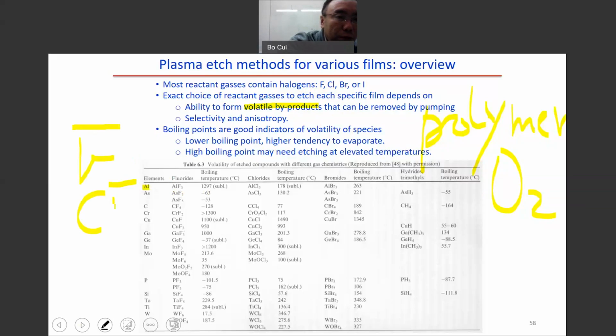For example, for the case of aluminum, if we use fluorine gas, for example CF4, there will be a chemical reaction, very easily, but the reaction product is aluminum trifluoride. This material has a very high boiling temperature, so even though there is a chemical reaction, the reaction product will stay on the wafer. Nothing will happen. On the other hand, if we use chlorine gas, Cl2, it will form aluminum chloride. For this one, the boiling temperature is 178 degrees, so it is volatile. This way, the etching will keep going because the etching product is volatile. It will be pumped away by the pump.